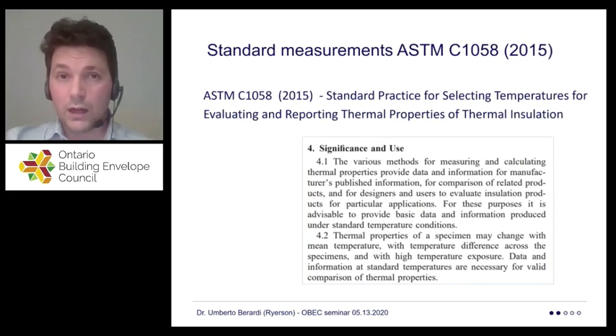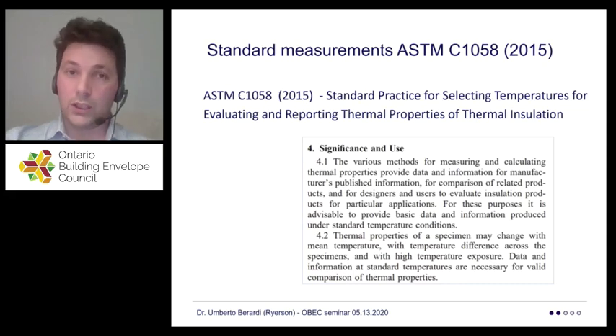And there are a few standards that have highlighted this element. There are standards like the one I'm reporting in this slide that say, pay attention, you should probably start using thermal conductivity values at the effective temperature at which that material will be used in the field. In other words, although people do not necessarily know these standards, they're saying that if you're using a material to insulate a pipe and the pipe is going to be at 200 degrees Celsius, you should have tested the material at that temperature. If your roof is going to be at -40, it's a good effort to try to understand what it means for a material to insulate at -40 degrees Celsius.